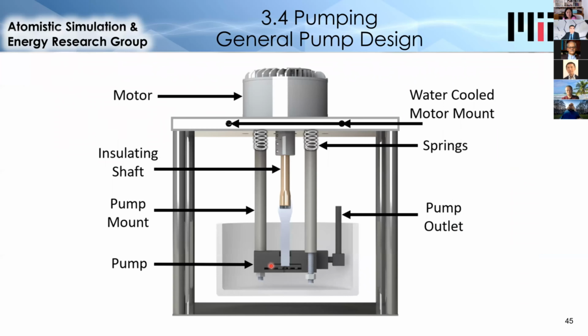So with the pump and flow meter designed, I needed to design a system to mount the pump and actuate it, cause it to rotate. And the main challenge here is that the pump is going to be above 2000 degrees Celsius, while the motor and the electronics need to remain below 100 degrees Celsius. So there's a 2000 degree temperature difference between the two.